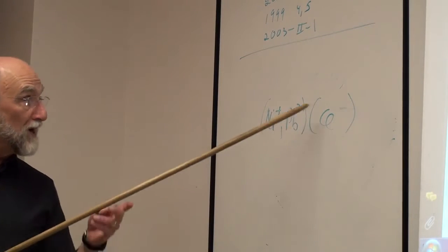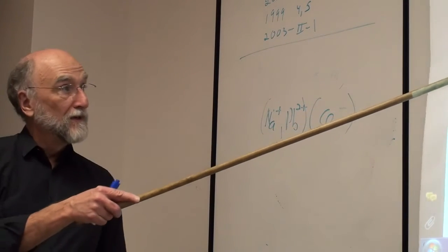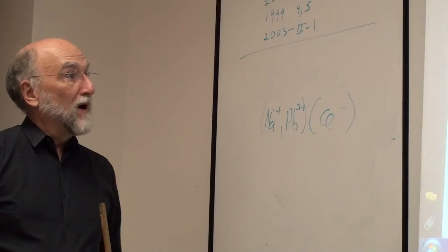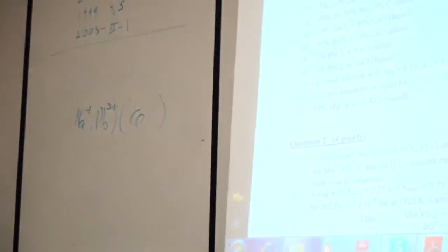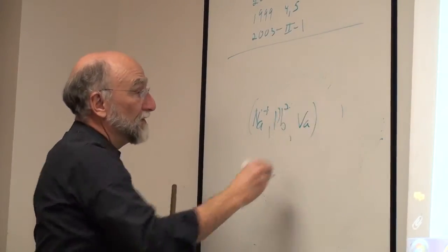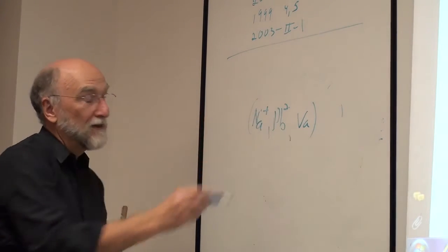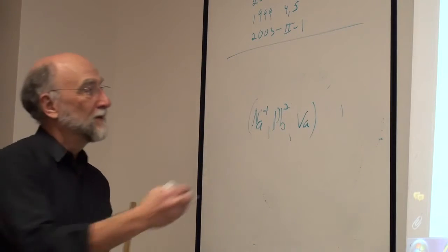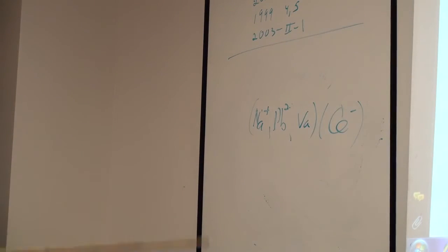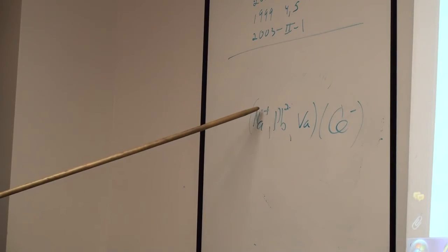So this is the Temkin model. The ratio of the sites is no longer 1:1, it's a little bit greater than 1:1. Locally, however, everything's fine. If you, however, put it into the solid, then the ratio has to remain 1:1. Okay, so if you put in a sodium and a lead, the lead 2+ has to form a vacancy on the cation sites. Every time you add a lead, you add a vacancy. You have the chlorine here. The lead replaces two sodiums. One lead replaces two sodiums and creates vacancies.